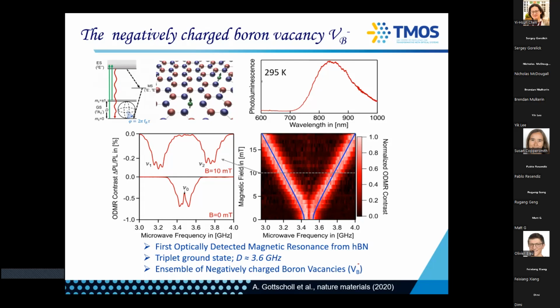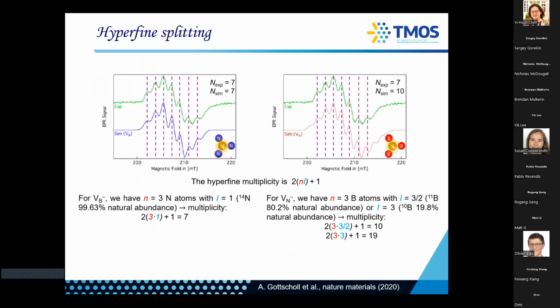And everybody was like, no, we're busy. This hBN is nothing interesting. So no, until we partnered with Vladimir. And so you can see here this ODMR, because it's an ensemble, you have 2 peaks corresponding to just strain-detuned boron vacancies. As you increase your magnetic field, the peaks would split. Okay. And because it's an ensemble measurement, we have a whole crystal irradiated. You can go back to the EPR and actually find the hyperfine straight away. That's how you know which defect you're imaging.